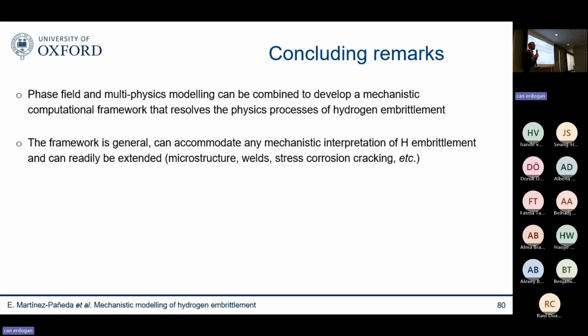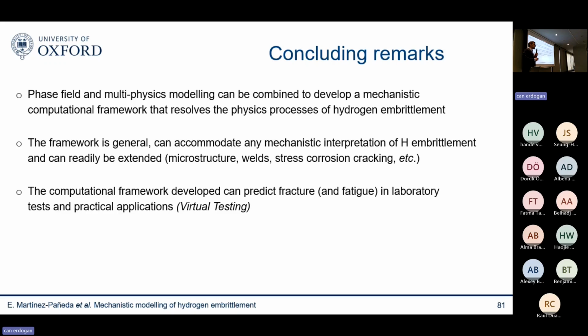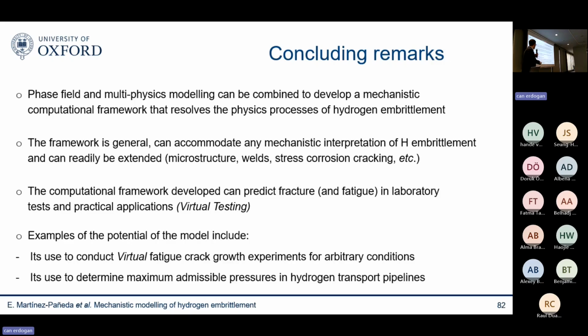And you can also combine it with microstructure simulations, welds, stress corrosion cracking. It's a very general framework in that sense. And the beauty of being a continuum level framework is that, well, maybe you don't get as much insight as lower scale simulations, but you are able to take this to the practical case. You can do virtual testing in hydrogen containing environments. And in fact, as I've shown you before, these models are now being used to design pressure vessels for hydrogen storage, and also to make decisions to determine under what conditions it will be safe to transport hydrogen in natural gas pipelines in the UK. That's all.